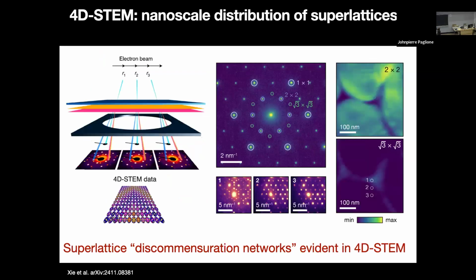Okay, so then we do 4D STEM, which is a scanning electron diffraction experiment. I won't go into too much detail here, but because the cameras for electron diffraction are generally much more sensitive and have a wider dynamic range than X-ray detectors, we can pick out that we not only have 2x2, the dominant, bright superlattice pattern, but we actually do have some root 3x3 in there.